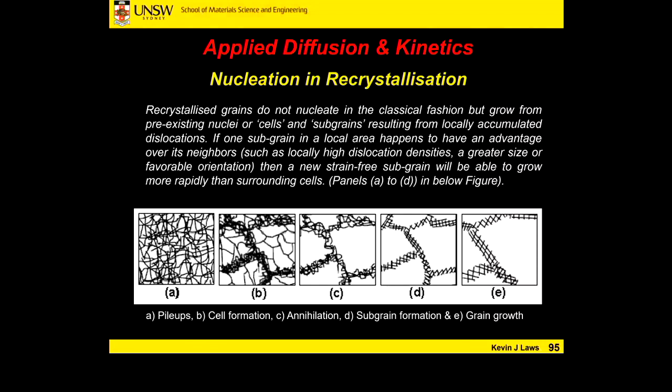When they hit a grain boundary, these dislocations get entangled with the grain boundary. If the next grain over the grain boundary has a different orientation, or the grain boundary is just a random jumble of atoms itself, that dislocation can't really proceed. It gets jammed at that grain boundary. It stops, and that grain just continues to change shape.